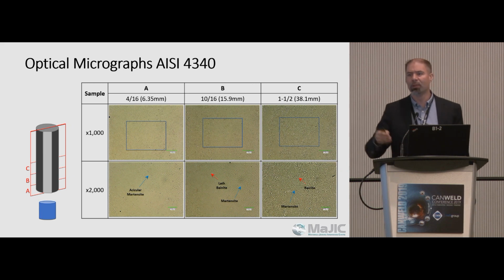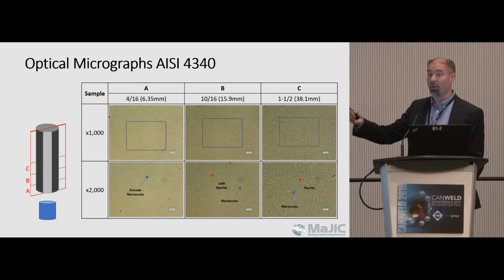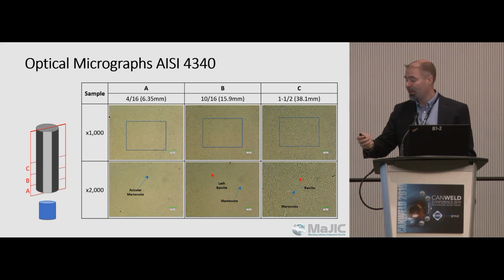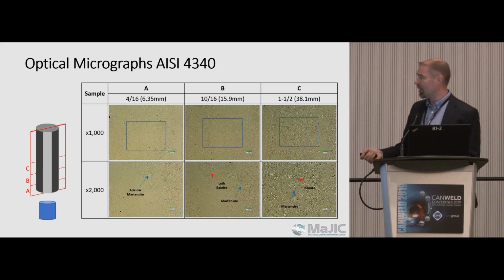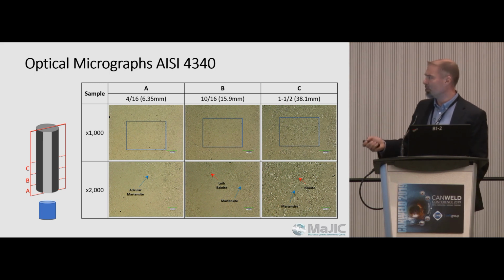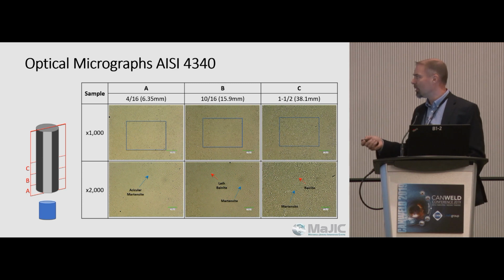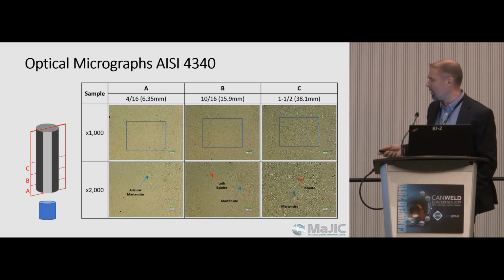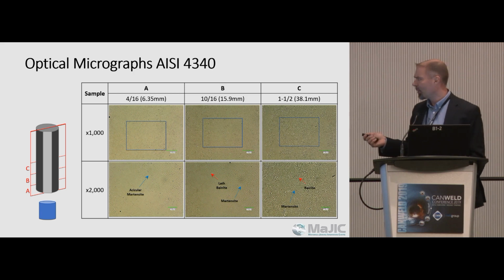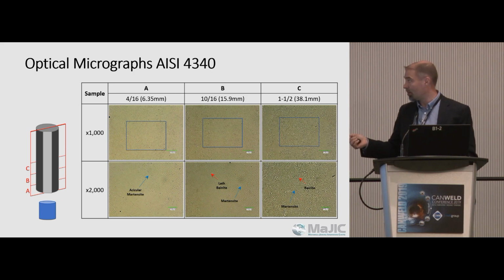Sectioning the sample and looking at the microstructure again confirms everything that we expect from such a sample. We see acicular martensite, very hard and brittle, in the closest samples to the end. We see some lath bainite along with martensite in the latter portions, and then just a martensite and bainite mix closer to 50-50 out at some of the cooler, slower cooling rates.